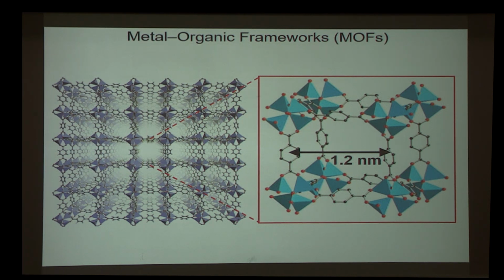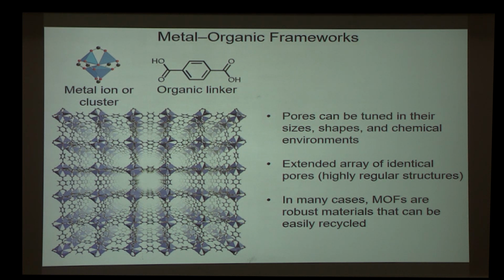They are part of an extended three-dimensional network where that same pore environment is replicated over a highly ordered structure in all directions. These materials are assembled by mixing together metal ions or clusters with an organic linker, and the metal cluster serves as a node to attach to multiple copies of the organic linker. In this particular example I'm showing you, the metal clusters are here, and the organic linker is here. And depending on which building blocks we select, the pores in these materials can be tuned in terms of their sizes, shapes, and chemical environments, which is quite exciting because we can think about precisely tailoring these pores to bind to a specific guest molecule of interest.